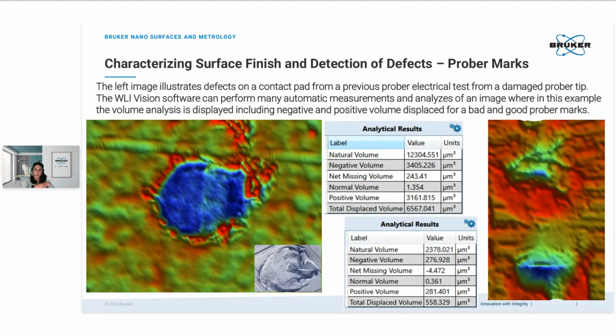Our next example here shows the automatic measurement of contact pads. Contact pads need electrical tests, which are commonly executed with electrical probers. These probers can leave prober marks, or not only can, they will leave prober marks on the surface. For example, if you have a damaged prober tip, these marks can have a negative effect on the contact pads. So with WLI, with non-contact measurements, you can automatically measure the prober marks, analyze their volume, and then receive the information whether the prober mark will have an impact on the functionality itself.